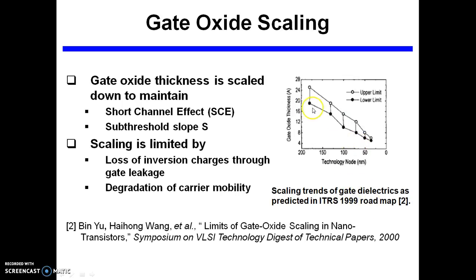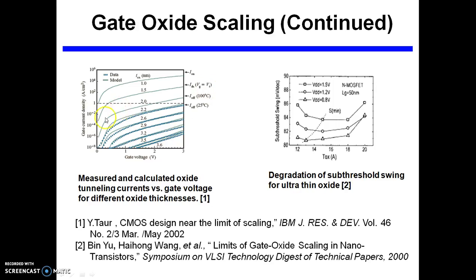As per the 1999 roadmap, if you are scaling the technology node from 50 nanometers onwards, upper and lower limits have been specified. This gate oxide thickness scaling limitation is because of the technology available, and scaling is also limited by loss of inversion charges through gate leakage and degradation in carrier mobility. As we scale gate oxide, because of the gate voltage there will be a tunneling current. Scaling from 3.5 to 3.2 down to 1 nanometer, the tunneling current increases and sub-threshold swing degrades as you go for the scaling — scaling oxide thickness to 20 angstroms will have a drawback on sub-threshold swing.